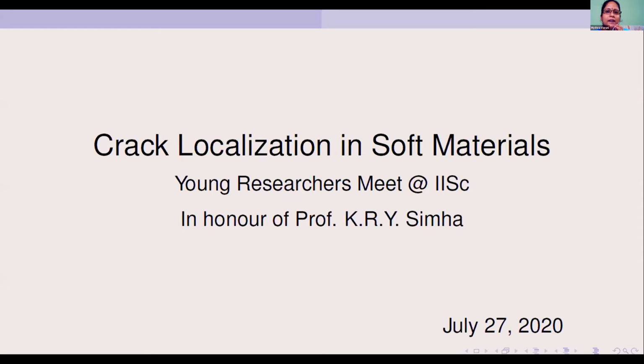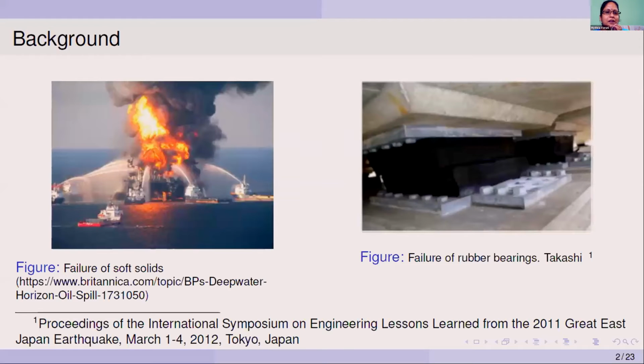So we illustrate this point here through these figures. This figure on the left shows the April 2010 explosion and the subsequent oil leak at the offshore oil rig in the Gulf of Mexico. It was found that the failure of foamed concrete, a soft material that was used in the oil well, triggered this oil spill and explosion. And this figure on the right shows the failure of rubber bearings which were used for seismic isolation of bridge structures in Tokyo. So it is necessary to predict the onset of damage, which is a precursor to failure, in order to ensure the safety of these structures.